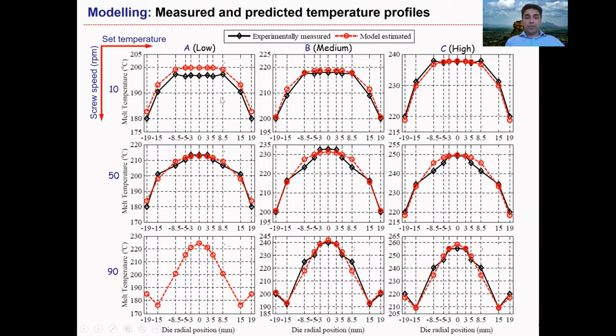This is a comparison between experimental and model estimated melt temperature profiles at different process settings. On this side the set temperature is increasing, A, B, C, and this is screw speed 10, 50, 90 RPM. You can see that the red line is the estimated one, and the black line is the experimentally measured one using the thermocouple mesh. So our model is pretty good, and we can replace the thermocouple mesh with our model.